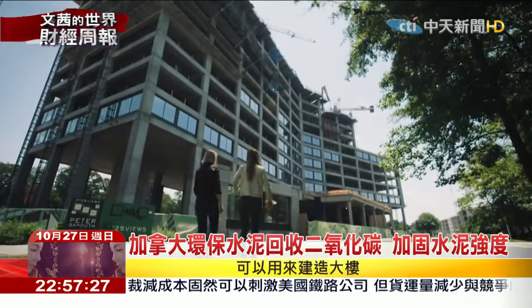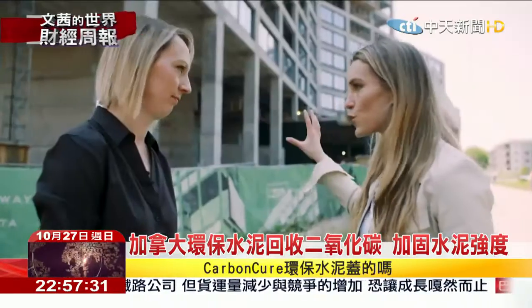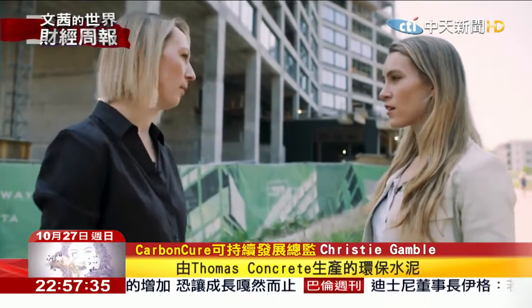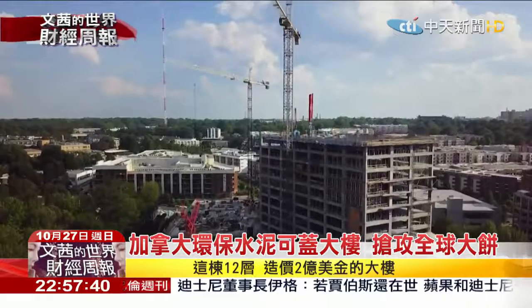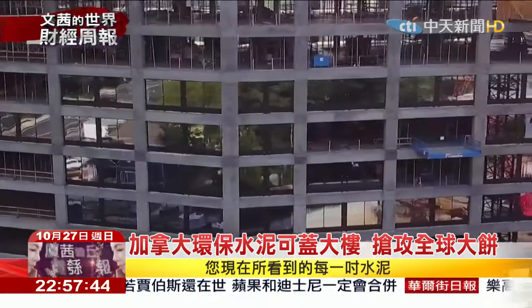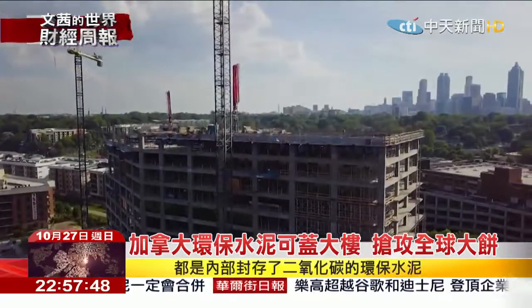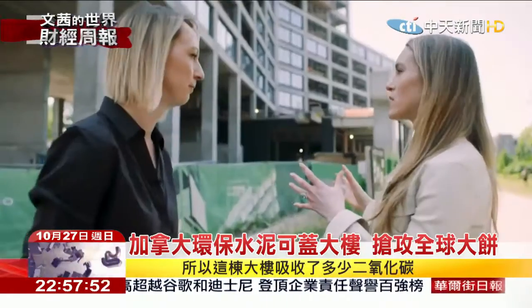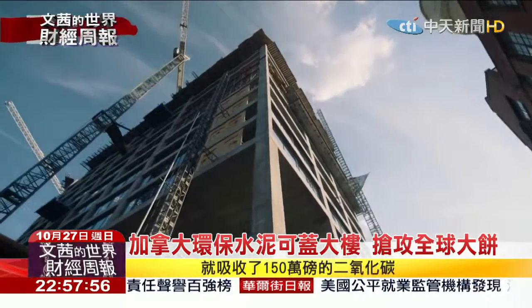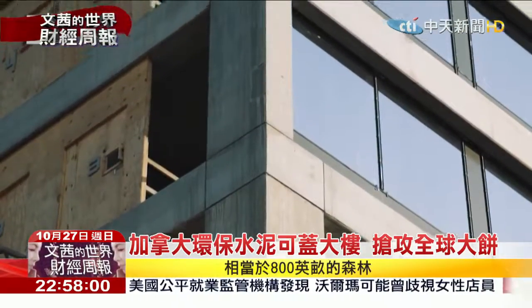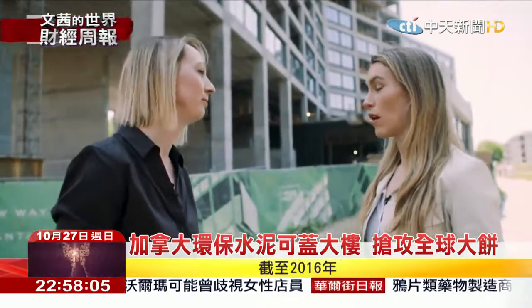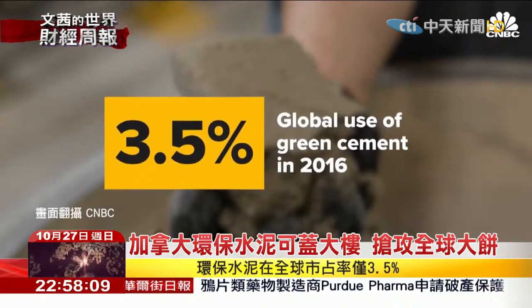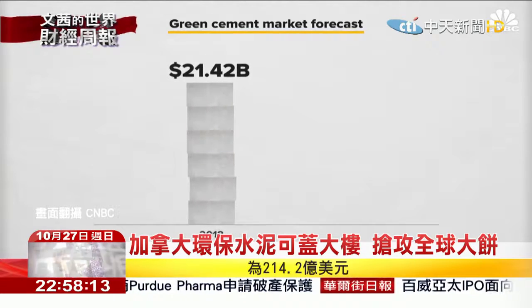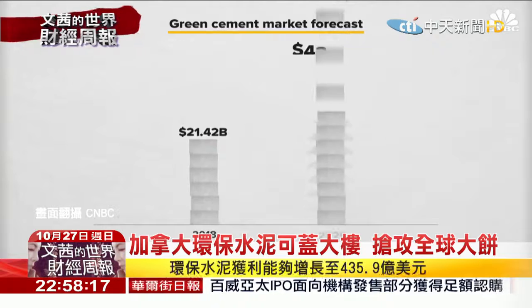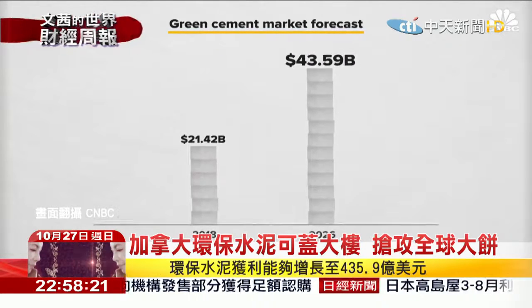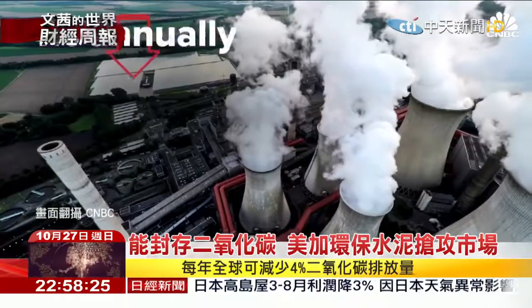This building behind us is all built using Carbon Cure concrete. That's right. It's 48,000 cubic yards of Thomas concrete made with Carbon Cure technology. A 12-story, $200 million development in the heart of one of Atlanta's trendiest neighborhoods. And every inch of concrete you see is infused with CO2. It's the largest structure Carbon Cure has ever worked on. So how many pounds of CO2 savings are we talking about here? In this building right here, it's going to be over 1.5 million pounds of CO2. If we could pretend that these were trees, it would be the same as 800 acres of forest sequestering CO2 for a year. Wow.